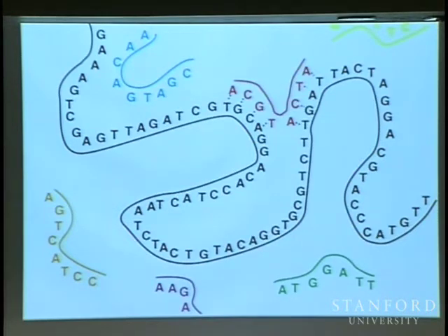So in fact, I'll describe a little bit about that. It turns out that in this virus, there is a place that sticks very strongly to itself, and we just don't use that part of it. Some people do it kind of successfully, but most of the time we eschew that part and leave that little part hanging off unfolded. So the sequence can have problems, and since it's very cheap to make these sequences, we would like to design our own in a computer and use those, because then we can optimize over this subsequence problem, and we do that for those DNA tiles. They're so short, they're made out of all synthetic DNA. Those are completely computer optimized to get rid of those kinds of problems. All right.